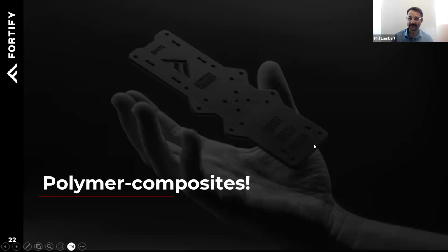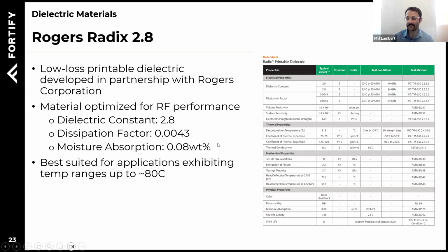I'm going to briefly talk about polymer composites and go into some details there. Just digging into the Radix 2.8 for just a second. Like I said, this is a material that's in production now. We use it for a lot of our devices that we manufacture. Our customers are getting a lot of value out of this. It has a dielectric constant of 2.8, dissipation factor of 0.0043 when characterized at 10 gigahertz, and very important, very low moisture absorption. If you're making dielectric lenses and you start to uptake moisture, you're going to start to really impact performance. So that moisture absorption, while it's not a primary characteristic, is really critical for our Lüneburg lenses. And these materials are best suited for applications exhibiting temp ranges up to 80 C. So not a super exotic, not a super high thermal stability material. But excellent for a large variety of applications.